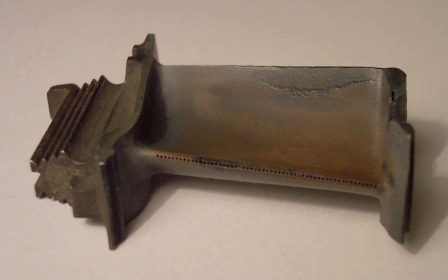Topic: failure mechanisms in thermal barrier coating systems. Failure of thermal barrier coating usually manifests as delamination, which arises from the temperature gradient during thermal cycling between ambient temperature and working conditions coupled with the difference in thermal expansion coefficient of the substrate and coating. It is rare for the coating to fail completely; some pieces of it remain intact, and significant scatter is observed in the time to failure if testing is repeated under identical conditions.